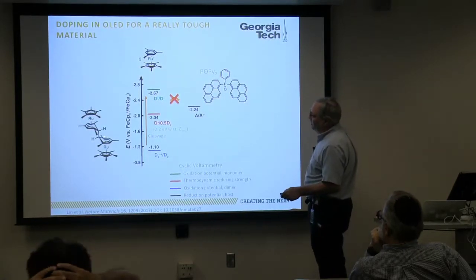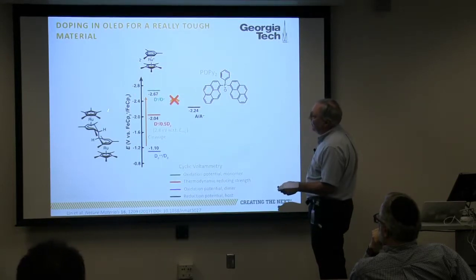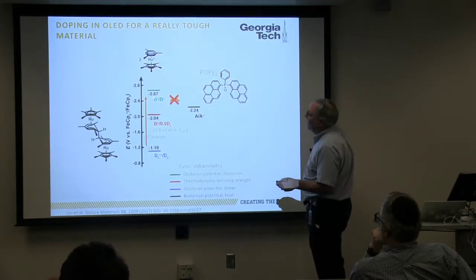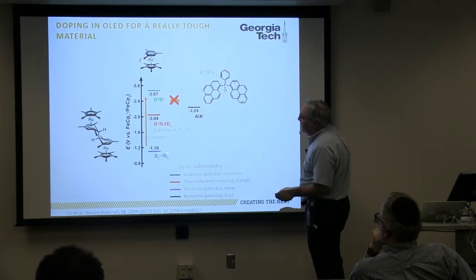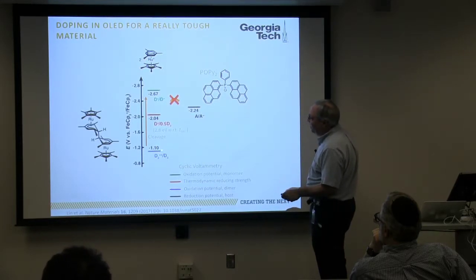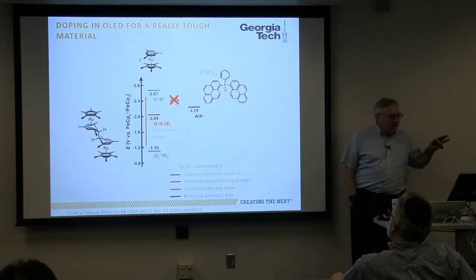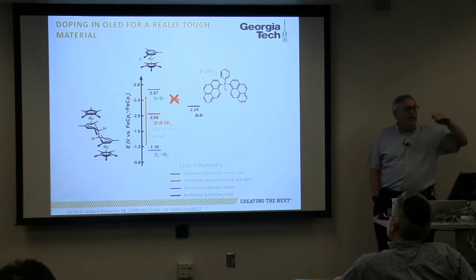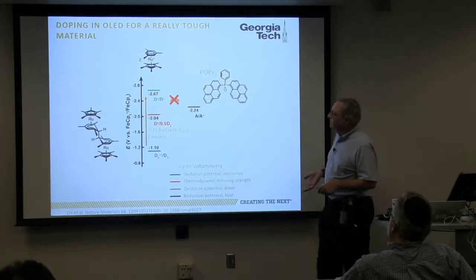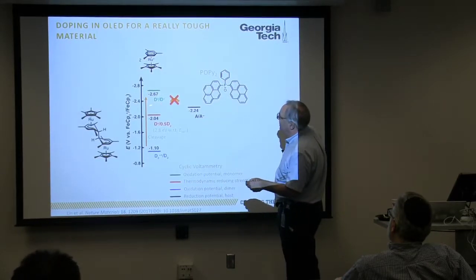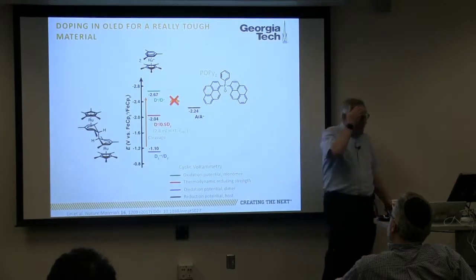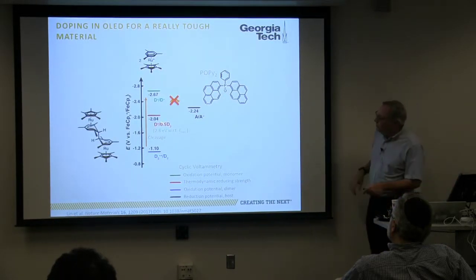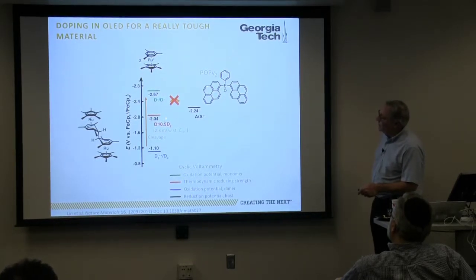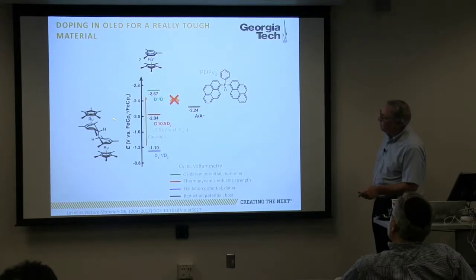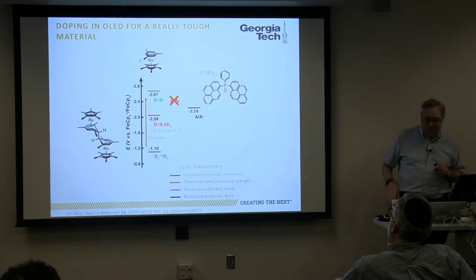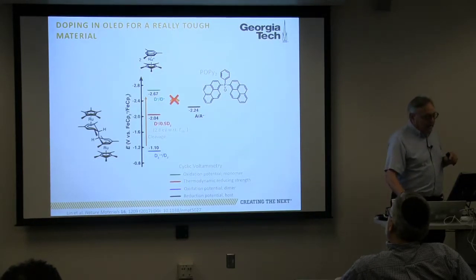Now, it turns out that these dimers, if we broke this bond and made a radical, which we can't just do cleanly, would be plenty strong to dope this. If we have this, to transfer an electron here is very much uphill. But we can calculate, through calculations and the experimental parameters that we have, the effective reducing strength of this dimer, which would be this reducing strength minus 1/2 of the energy required to break that bond. And the long story short is that we shouldn't be able to do this. It's uphill per electron by 0.2 volts, and for the overall reaction of one of this plus two of these, uphill by 0.4 electron volts. So we shouldn't be able to do that, but we tried nonetheless.